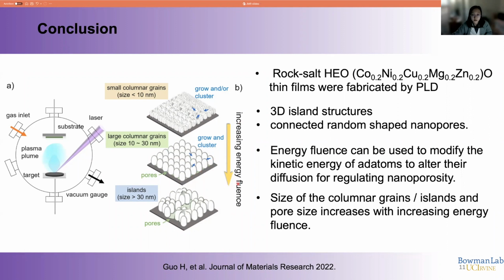With the increasing energy fluence, the columnar grains tend to grow and cluster by the force of deposition-driven impingement and the capillary-driven surface coalescence, and these columnar grains or islands will collide and grow, making larger islands and leaving larger nanopores. So the size of the columnar grains, islands, and the nanopore size can be regulated using the energy fluence.